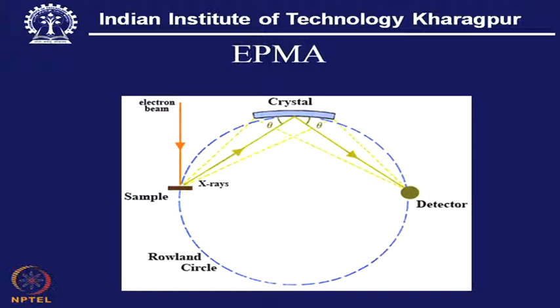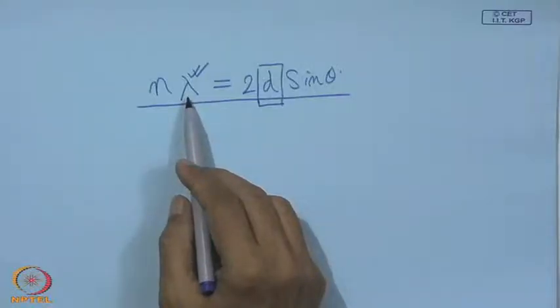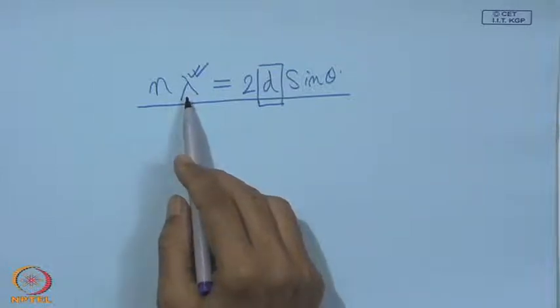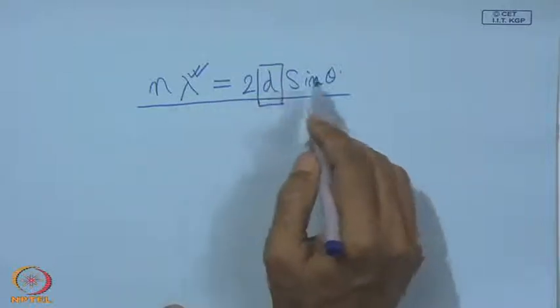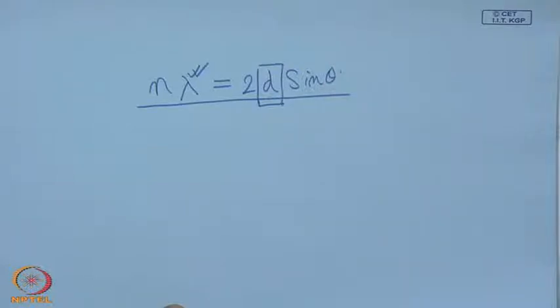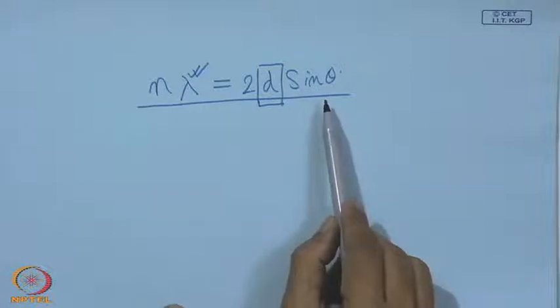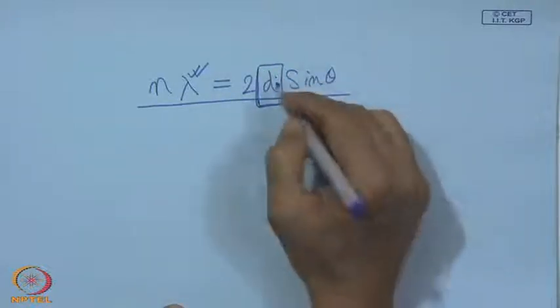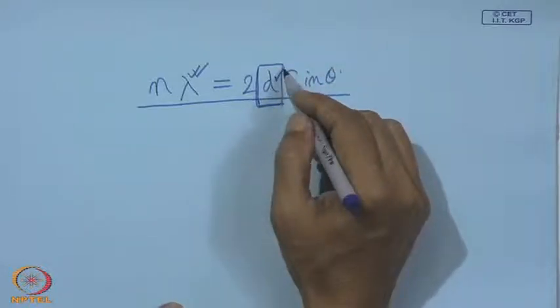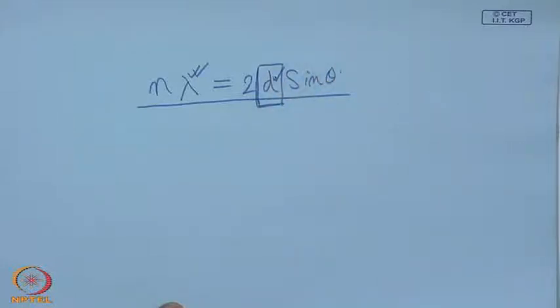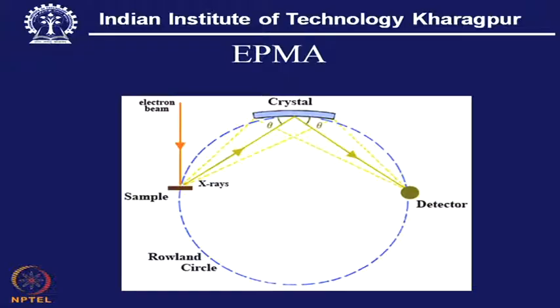Now, depending upon the value of lambda, this value of theta will change. That means, if lambda changes because of a particular material, it will be detected through this sin theta. If we change the orientation of this crystal, then a particular wavelength will be captured, and that will follow this particular equation. That will correspond to a particular d value, which is a characteristic feature of one particular element, and this way we can detect different elements, except a few of the very light elements, but most elements can be detected.